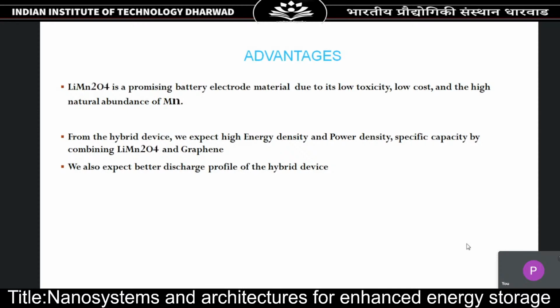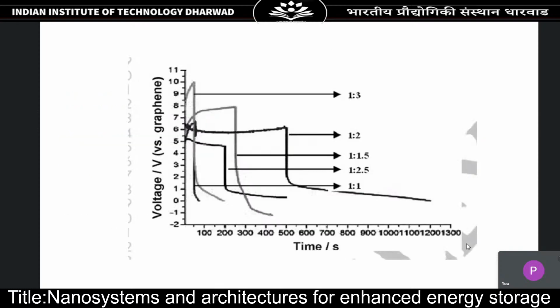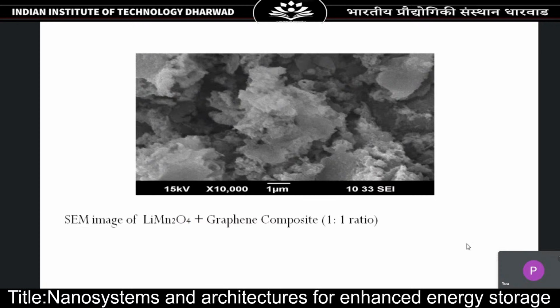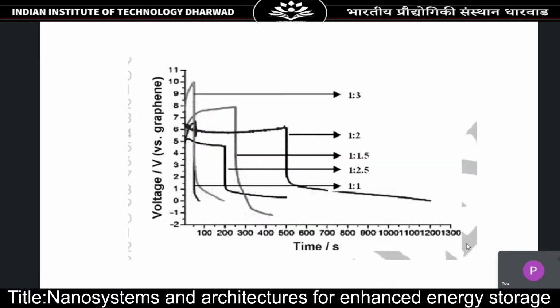Lithium manganese oxide is a promising electrode material because of low toxicity, low cost, and high abundance of the lithium and the manganese as well. What we expected was high energy density and power density if you combine the lithium manganese oxide and graphene. You can see some of the images. This is the SEM image of the lithium manganese oxide and graphene composite in the ratio 1:1. And this is the charging profile and the discharge profile.